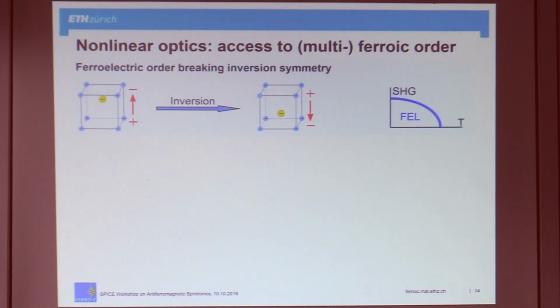Okay, so second harmonic generation on ferroics. As I said, any type of ferroic order breaks some point symmetry. Here, ferroelectricity breaks inversion symmetry. If you apply the inversion symmetry to a ferroelectric, the polarization reverses. That means once a material undergoes a ferroelectric order, suddenly there is a contribution to this frequency doubled signal, background free. So this is really nice. The signal is small, but there's no background you have to separate it from.